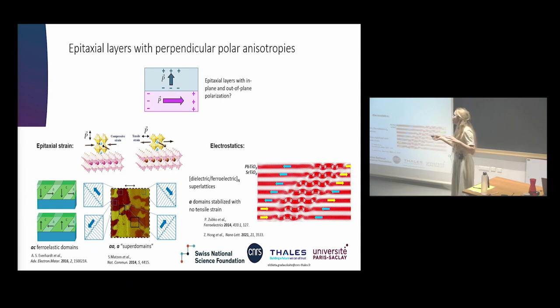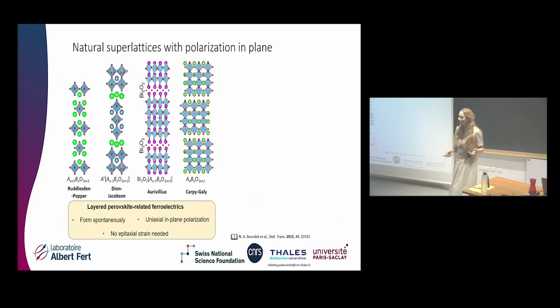And in that way, we can electrostatically push the polarization in the plane of the film. But now, as much as I love growing PLD films, it's still quite tedious. Imagine to layer these materials, it takes time. It's not a very easy solution. And what instead I would like to propose in this talk is that we can create such similar electrostatic superlattices naturally, because in fact there are these layered ferroelectric materials based on perovskites that form such superlattices naturally.